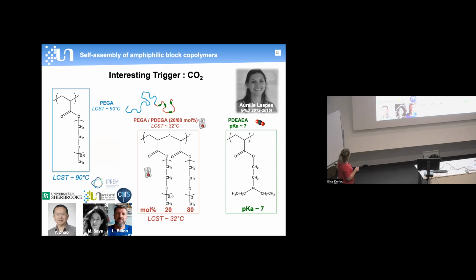copolymerization of polyethylene glycol acrylate and polydiethylene glycol acrylate with an LCST that can be tuned at about 32 degrees C, depending on the composition of these two units, and a pH sensitive unit, which is in this case the diethylaminoethyl acrylate, with the amine, which can be protonated under acidic condition,